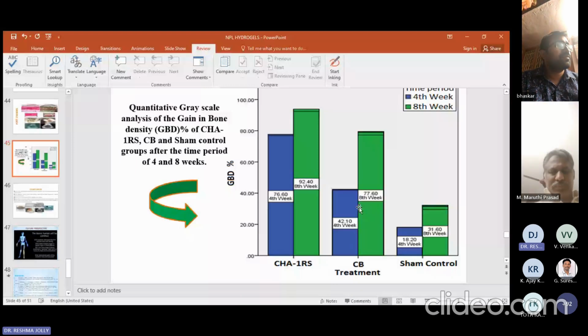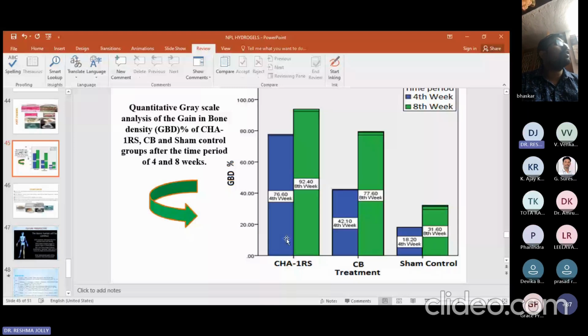As we can see, after 8 weeks, CHA-1RS was still visible in the histopath slides, right? So I think after 10 weeks or so, it could be degraded completely and it could show 92 or 95% bone formation. And in this group where we left it empty, we did not treat it with anything, natural healing was 18% at the 4th week, and after 8 weeks it was 31%. So a significant improvement in the gain in bone density was seen in the case of our material.